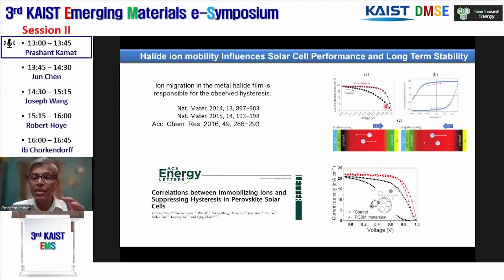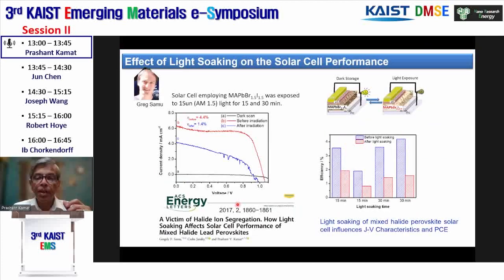So this is not an issue anymore, but this just points out one small thing: this ion mobility, especially halide ion mobility in this solar cell, is an important thing. And here is a correlation between immobilizing ions and suppressing hysteresis, one of the early studies on this. We looked into the mixed halide perovskites very early on, this is in 2017, where we showed that if you make a cell with just a plain mixed halide perovskite, these ions move and they segregate. And as a result, you can see here a decrease in the performance of the solar cell.